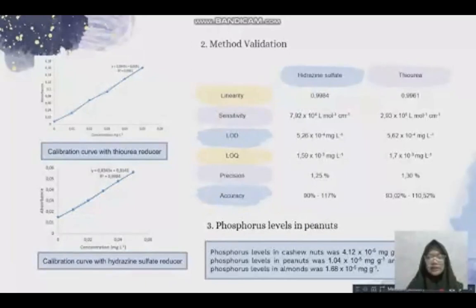Precision is the result of repeatability by the same tools and analysis, obtained at 1.25%. And accuracy is expressed by the percent recovery obtained between 90% until 117%. For the validation of the thiourea analysis method, the linearity is 0.9961. Looking at the validation of the analysis method carried out, the better reducer is hydrazine sulfate.